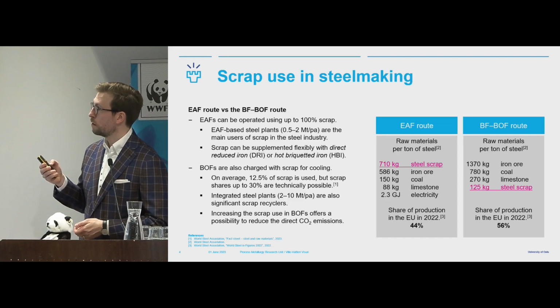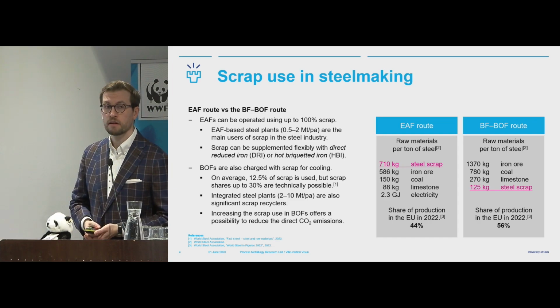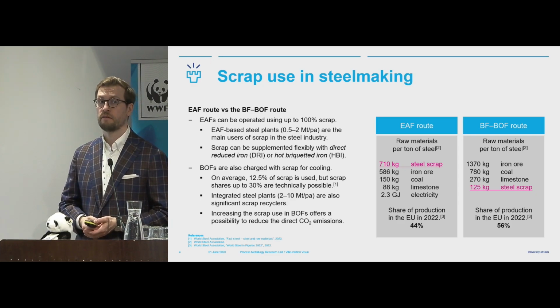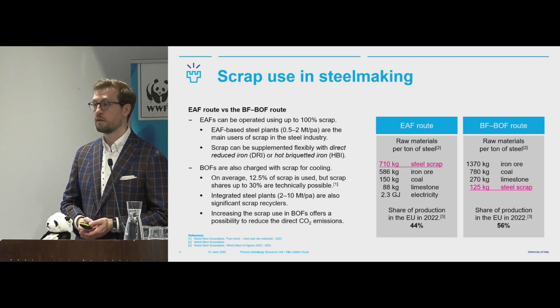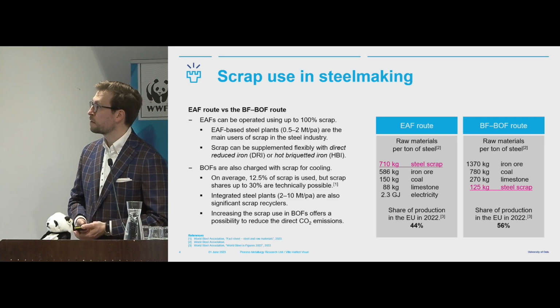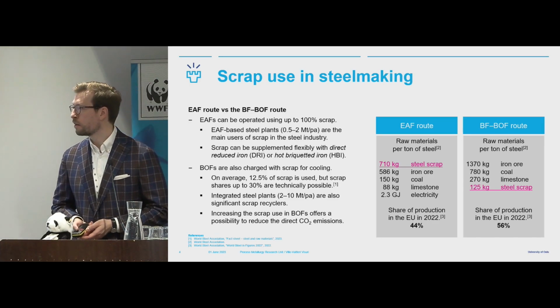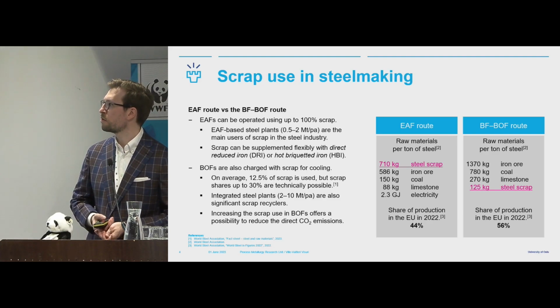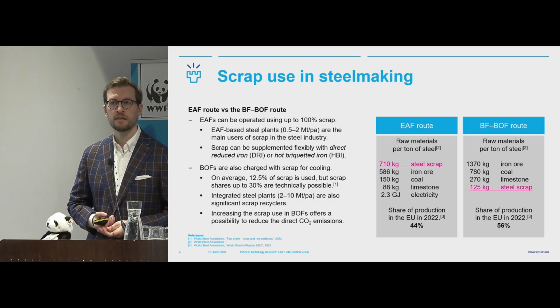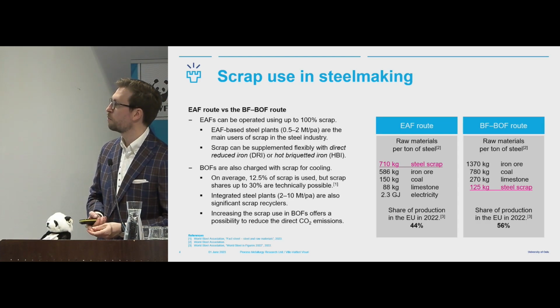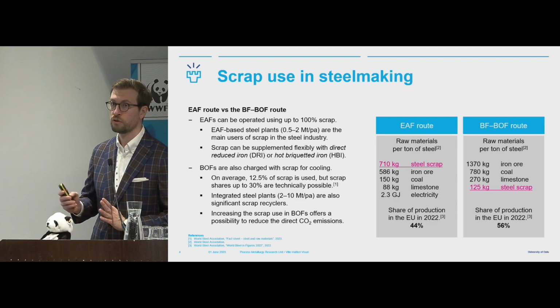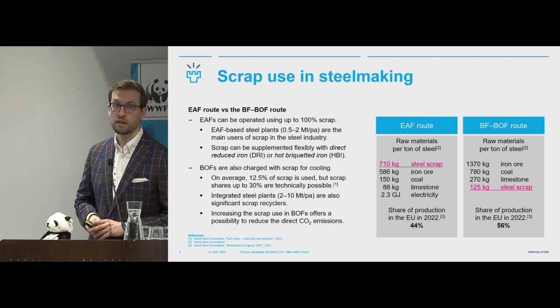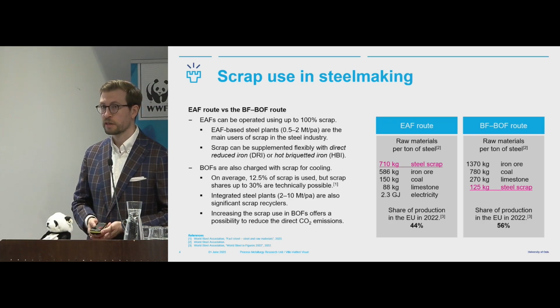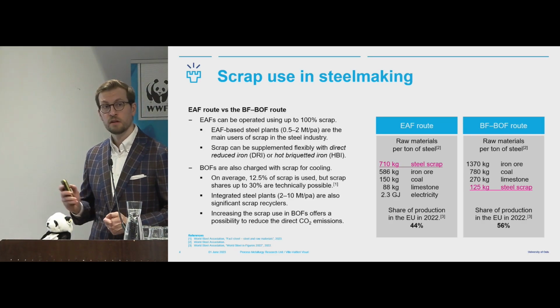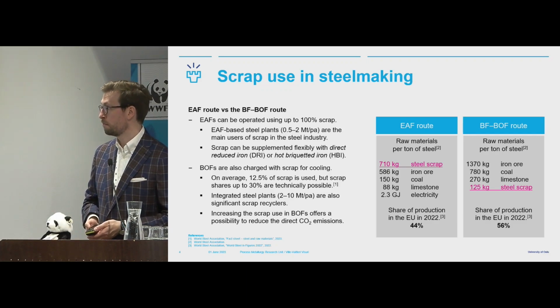This is something that I wish to highlight here, that also the integrated route uses scrap, and because the steel plants are typically much larger in size, they also are significant recyclers of steel. And there's some potential here. I've found this figure that 12.5% scrap would be used on average in the basic oxygen furnace, but I think this is a lowish figure, and I don't believe it myself. I think 20% would be closer to the truth. But the technical limit would be around 30%, and using post-combustion technology, we could have even higher shares of scrap. So there's enormous potential to use more scrap in integrated routes.